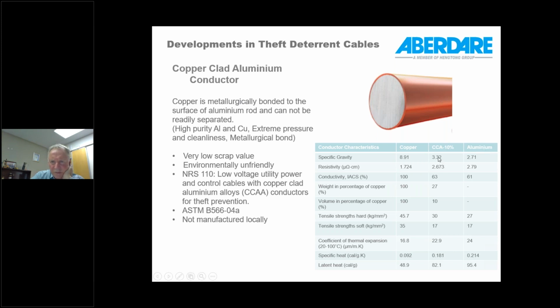Specific gravity, CCA is much closer to aluminium than to copper. Resistivity and conductivity is roughly the same as aluminium, as you can see here. Copper is 100% and CCA is 63% and aluminium 61%. The weight as a percentage of the copper is low for CCA, 27% that of copper, and the volume of copper is only 10%, as defined by the 10% name that's given to this particular version. You also get a 15%, but I would say 10% is probably the most used.